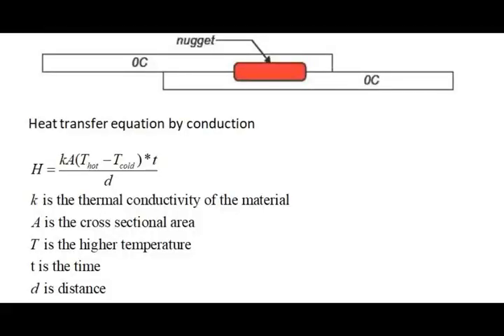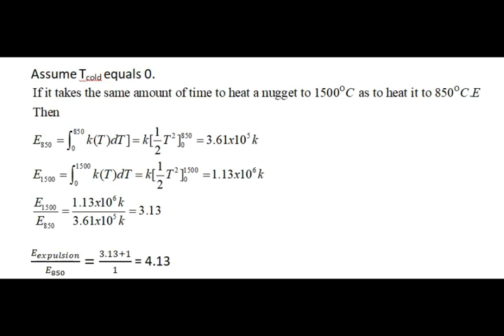Assume the metal that surrounds the weld is 0 degrees Celsius. The energy to heat the weld to a certain temperature can be calculated like this. Let us assume the imaginary nugget is surrounded by 0 degrees Celsius metal, and the conductivity is represented by a constant K. The capital T is the temperature of the weld. The energy needed to heat the faying surface can be calculated by integrating kT dt from 0 degrees Celsius to